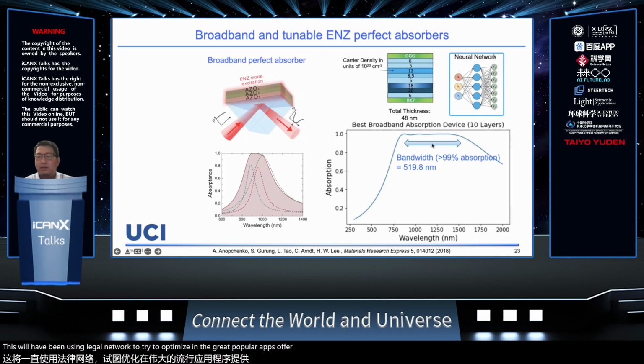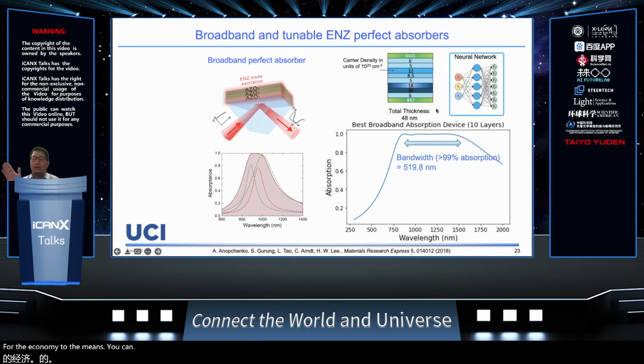For example, here are some of the results. You can see that in a 10-layer structure, we can use a neural network to make a broadband absorber for around 520 nanometer, which is really a large band with perfect absorption here. And the total thickness is only 48 nanometer. It means you can have a really ultra-thin ENZ material and at the same time have a broadband response using this kind of neural network design.